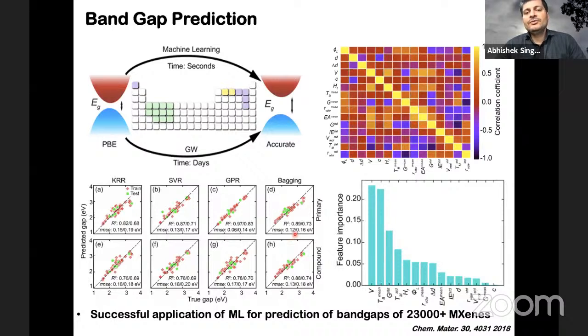0.12, and R square was about 0.89. This was a bagging model. We used various algorithms, of course KRR, SVR, bagging, and GPR. And we found that GPR turns out to be the best approach to get a highly accurate model.